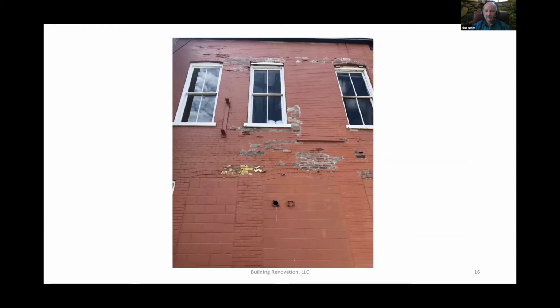Here we have a building that has been painted and repainted, and this is 1 year after the painting. So it has been recommended that they put an elastomeric coating on, so they did. That's why we can see these brick shards hanging off of the elastomeric coating. They never went to the cause. The cause is the lack of flashing behind the gutter, and the gutter freezes over every winter because of the lack of insulation upstairs and lack of proper ventilation on a flat roof. So they just keep on throwing repairs and money at this building and helping the building to continue to deteriorate when they didn't go after the cause. This one's in Allegan.